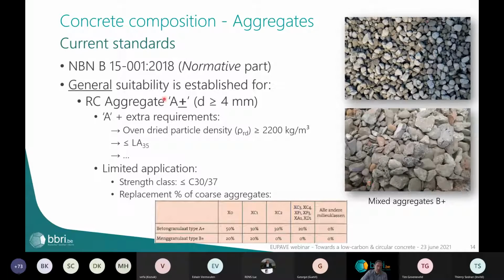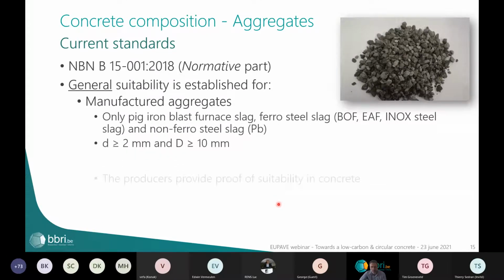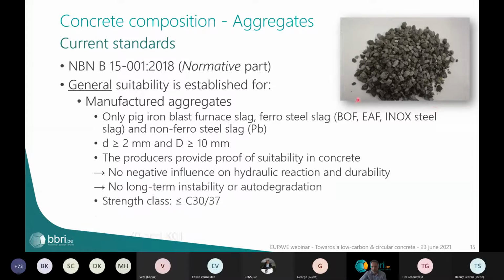Also for the B aggregates, the mixed aggregates, the standard already gives guidelines of how to use them in concrete. So you can already use them, and the same is true for manufactured aggregates, but it is very limited regarding the composition. You cannot put whichever slag into the concrete. It's limited to certain types. Also, the fractions are limited, and the producers still have to provide the proof of suitability in concrete, that the aggregates have no negative influence on the properties of the concrete, and it is also limited in strength class and in the application. You can only go up to XC1, which is a very limited field of application of these aggregates. But it's already possible to do this.